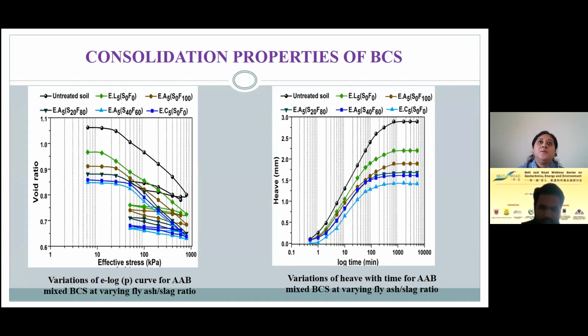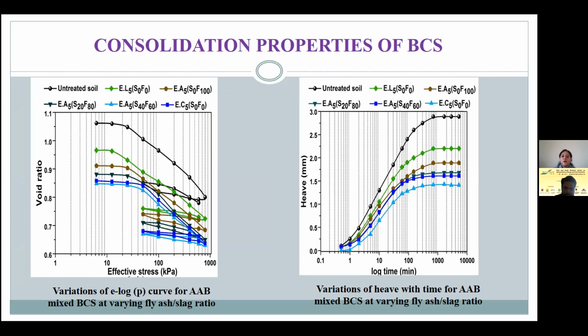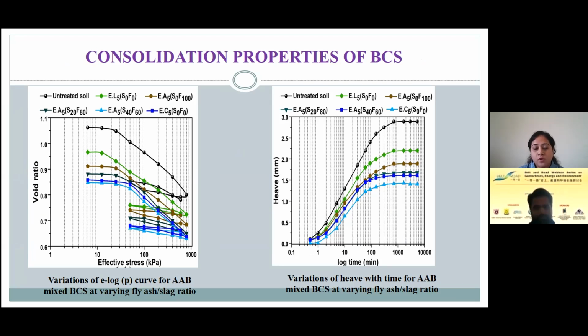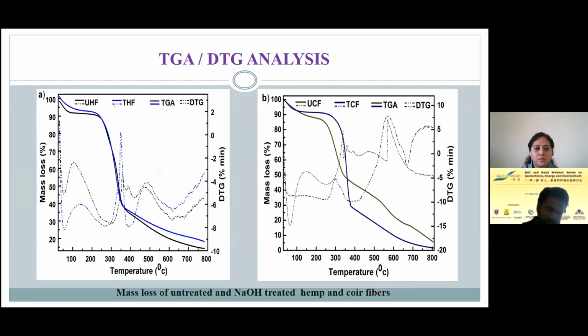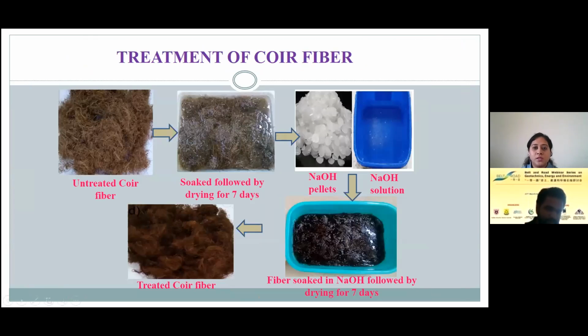Yes, this natural fiber degradation was definitely a real challenge. But when we are treating it with this sodium hydroxide, as I showed you in the process, we are soaking it in this sodium hydroxide solution. When we are treating it with the sodium hydroxide solution, although we have not exclusively conducted the durability studies and we are in the process, the strength of a single fiber increases extensively. But yes, it is definitely a natural fiber, so with time, after years, it is bound to degrade. That is always a challenge.